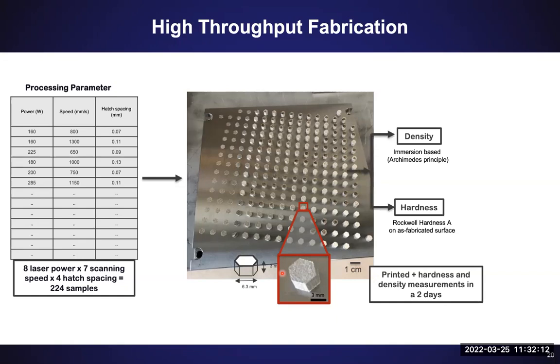Once the samples are built and taken off the plate, we needed a way of screening these samples because the dynamic tests we do are very expensive and time consuming, and we weren't going to test all 200 samples. So some of the low-hanging properties that we can use to screen for these materials involve things like density and hardness. Density because a lot of the build parameters lead to samples that have a lot of porosity in them, and we didn't want that initially. And then hardness because that can be a quick screening way of seeing if this material is going to even pass a baseline strength criteria or not.